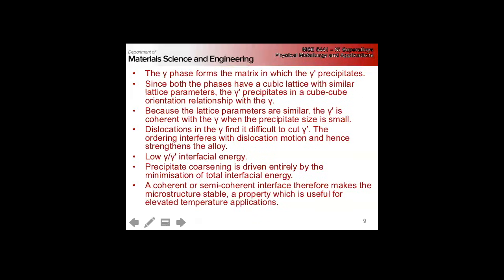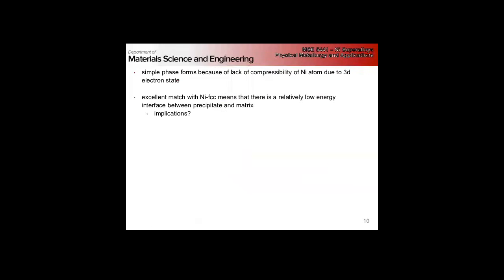This coherent or semi-coherent interface is really important for maintaining stability at elevated temperatures. The more low energy the interface, the less mobility it has, and so we maintain a more stable structure. Okay, so I sort of answered my question already, right? What are the implications of the low interfacial energy?